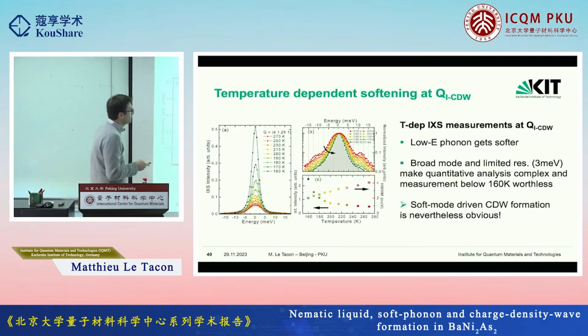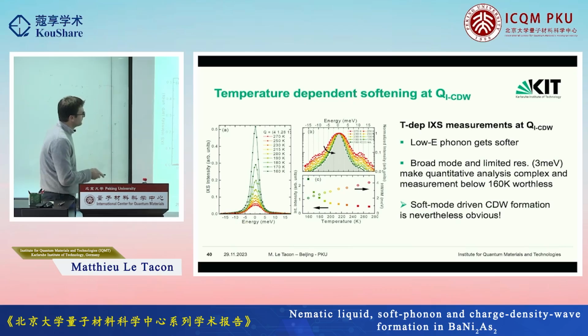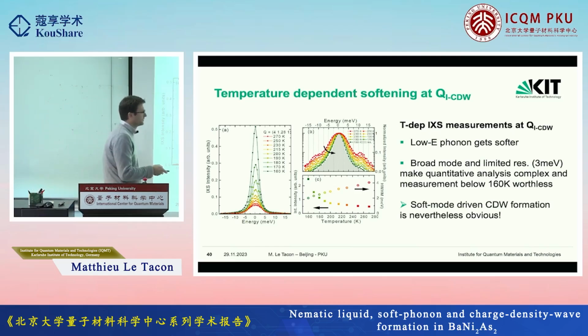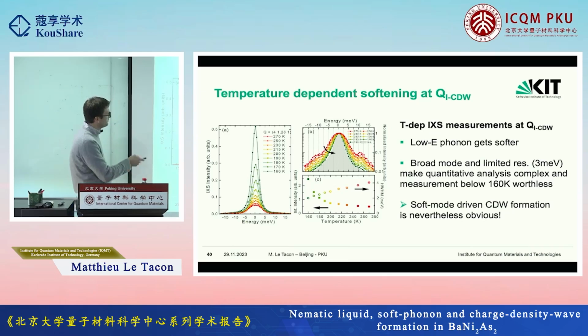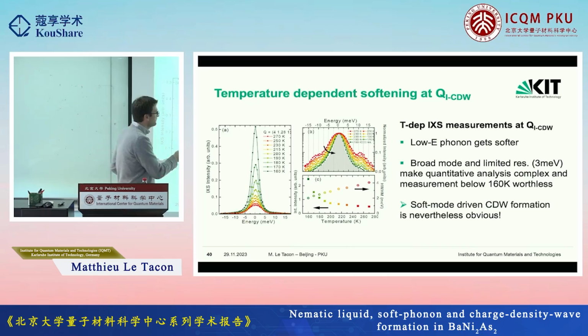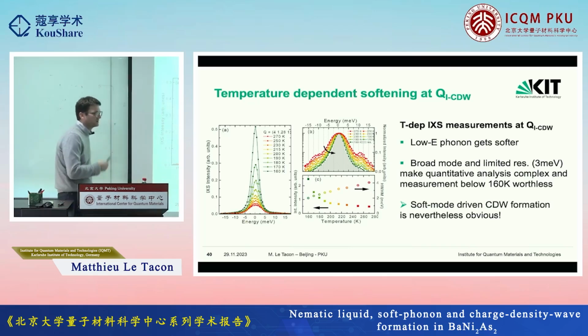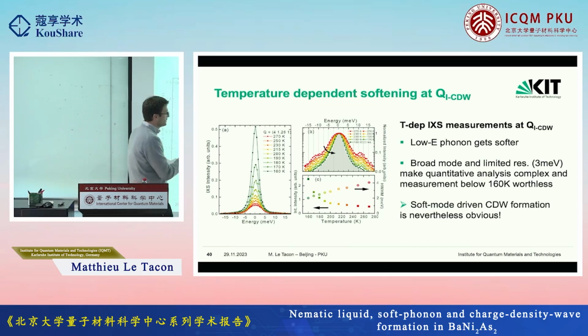And this is really tricky now, because with that kind of resolution, basically what you see upon cooling is a very strong central peak. So the way to see whether the phonon is completely soft or not is to compare this inelastic scattering profile with the resolution in gray. And you can see that from 270K, where there's clearly a softening, and below roughly 160K, we cannot really distinguish. It seems to be a bit broader than the resolution, but it's really, really hard to extract from that a meaningful energy associated with that.